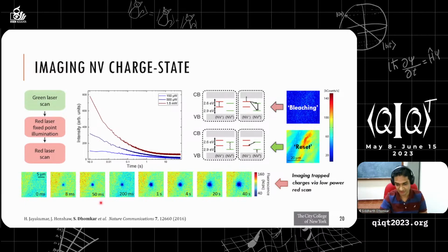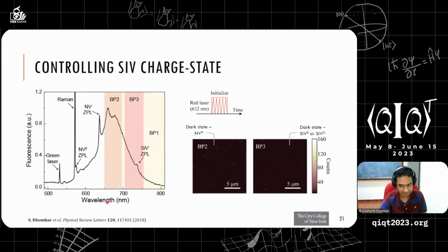Without destroying it, because this has been generated by a high power laser, something like this, and has been read with a very low power laser, a few microwatts, few tens of microwatts. And this is not only related to NV centers. This is a property of any deep defect which sits inside a band gap. So this is valid for any other defect.